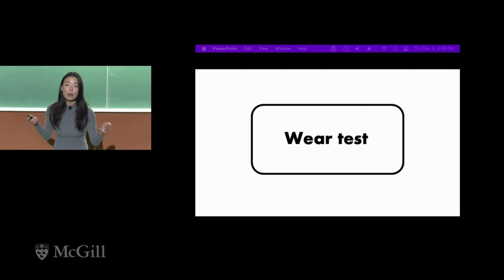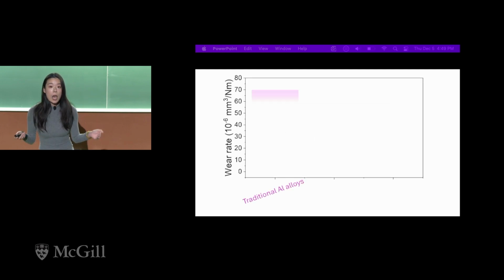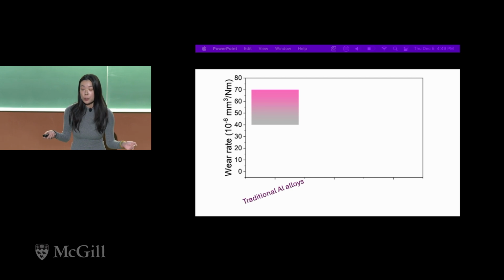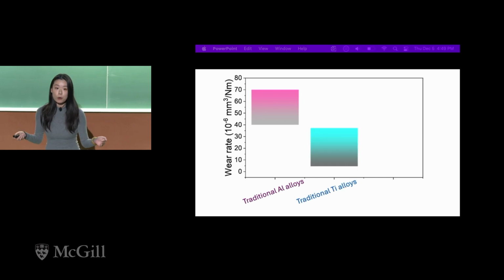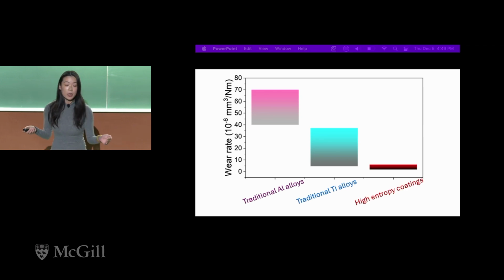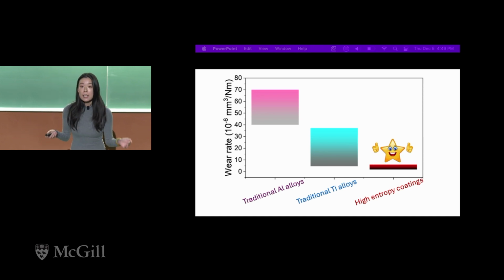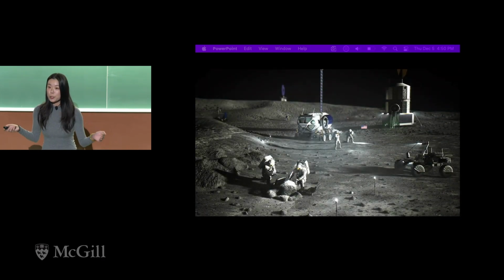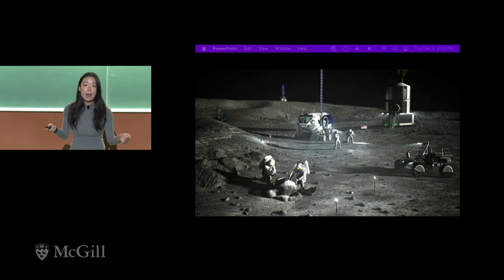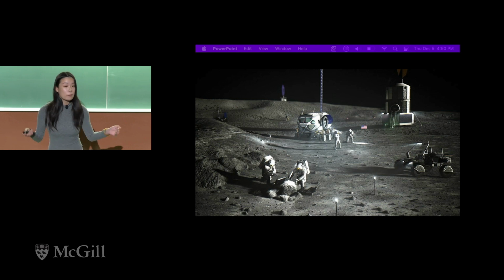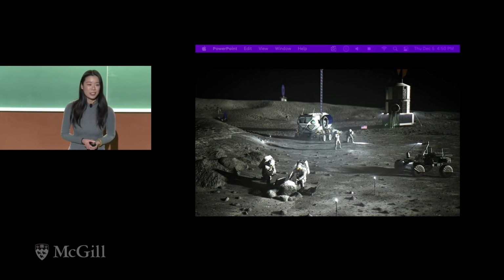First, let's consider some traditionally used materials. Aluminum alloys have a wear rate ranging from 40 to 70, while titanium alloys improve this range to 5 to 35. Our high-entropy coatings, however, show a significant reduction in the wear rate, ranging from 1.5 to 6. This indicates that this type of material has much less material loss compared with the traditionally used materials, highlighting its great potential to be used in space transportation applications. And maybe one day, by continuing study, we will have our transporters operate longer and more effectively in outer space. Thank you.